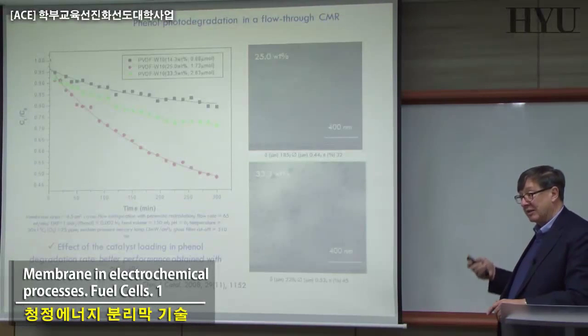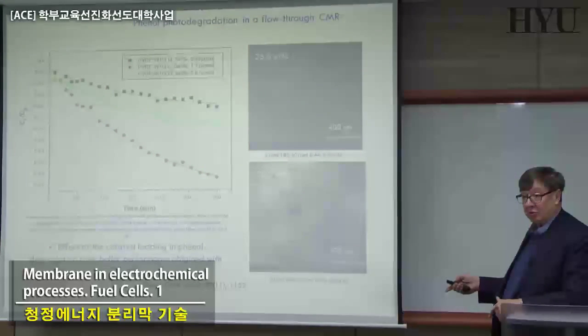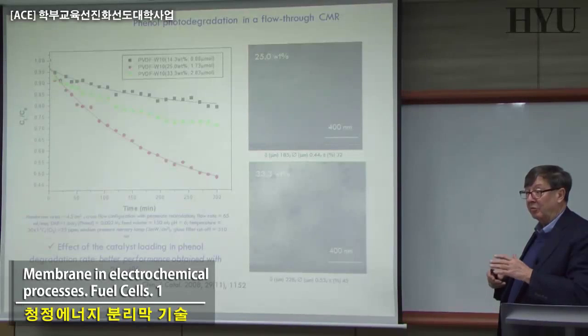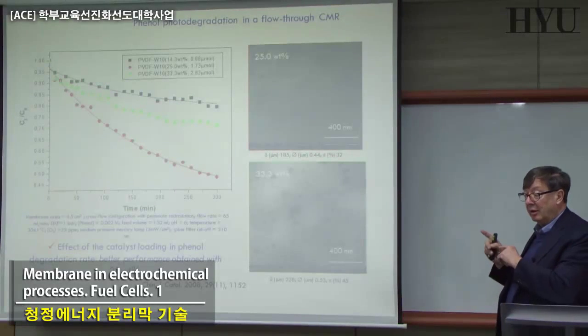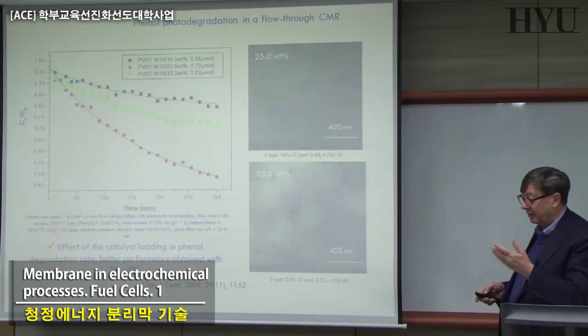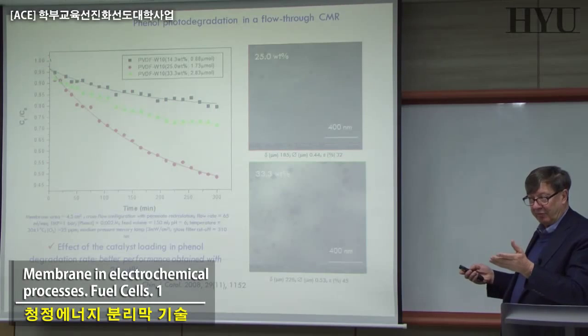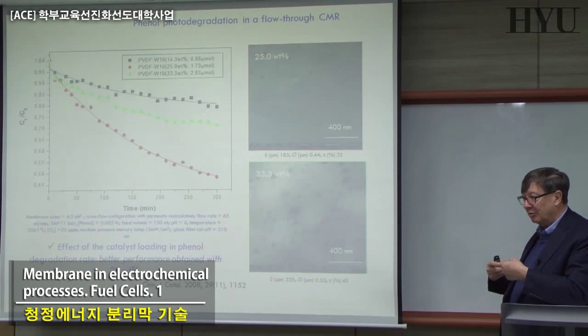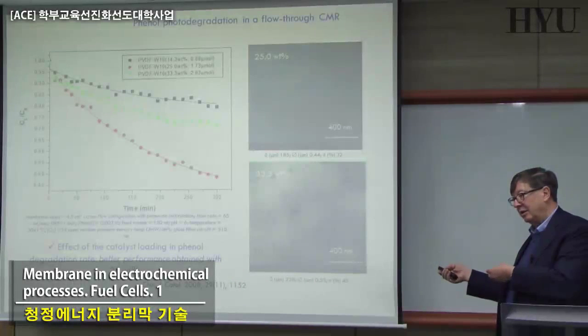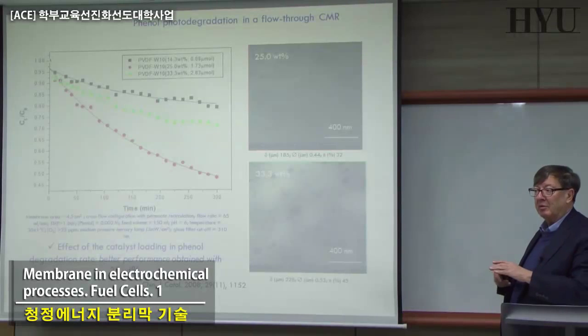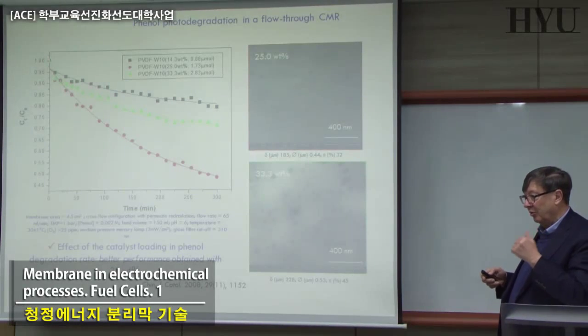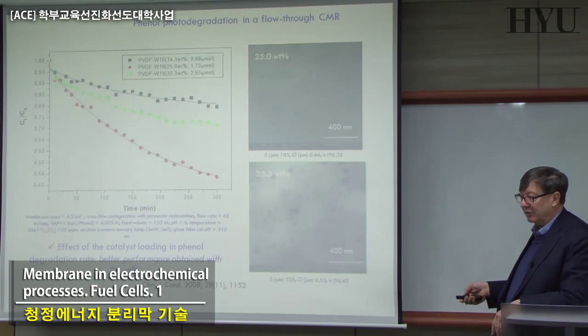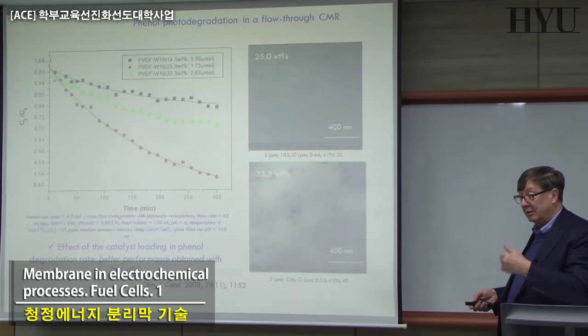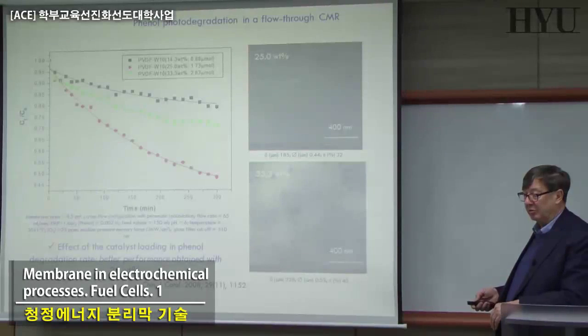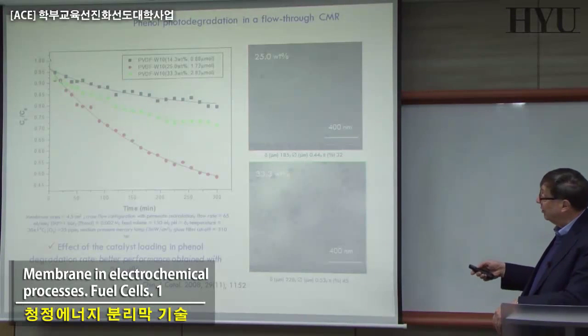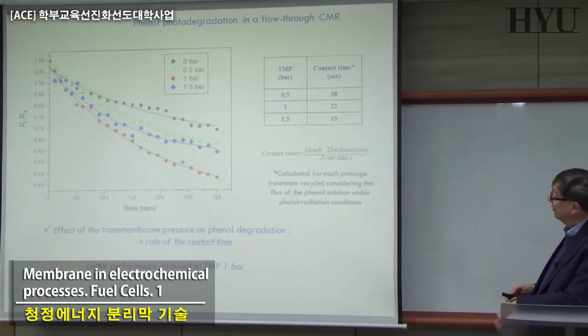You can have here, as we discussed last time, a diffusion control or a kinetic control system. Diffusion control means that if you charge too much, part of the catalyst is there but does not work. To have a catalytic reaction, you need a physical contact between the substrate, the reactants, and the catalyst. And if you have a system that is too dense or a block system with no easy permeation, you're having trouble. So there is trouble in leakage, trouble in mass resistance, it is not easy to arrive at the catalyst, etc. All these things mean that you have to work in different conditions and check the situation.